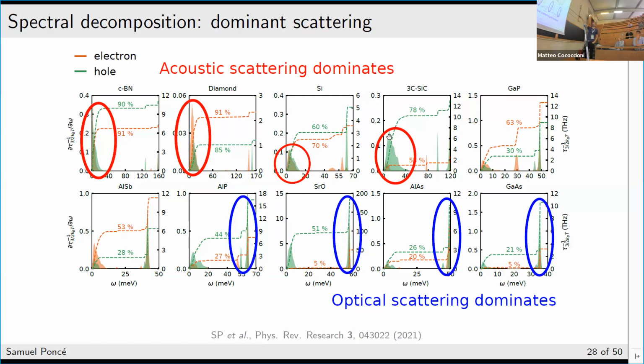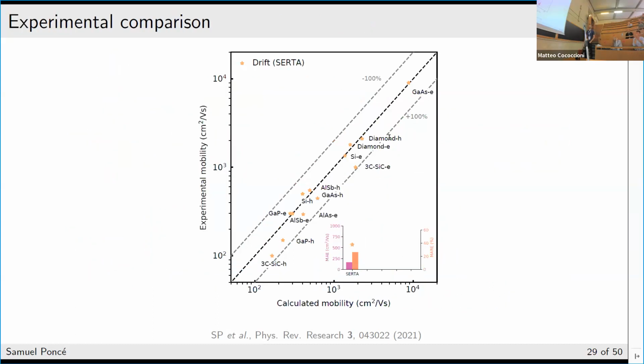For stiff materials like diamond, cubic boron nitride and so on, you really have acoustic scattering dominated, while for materials like gallium arsenide, aluminum arsenide, and so on, you have optical scattering dominated. In principle, you cannot know in advance, and so it's very important to include all the possible scattering if you want to be predictive. You can also see that there are some materials in which both acoustic and optical are important.